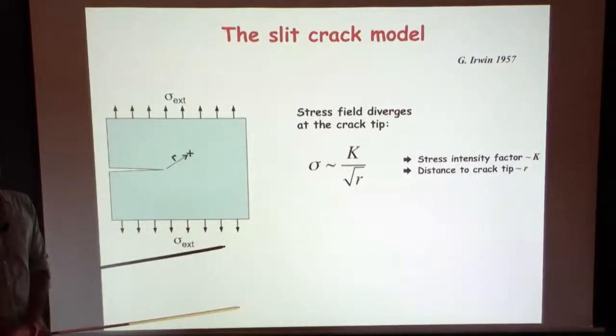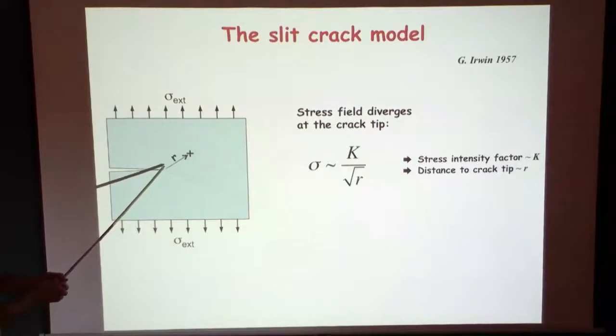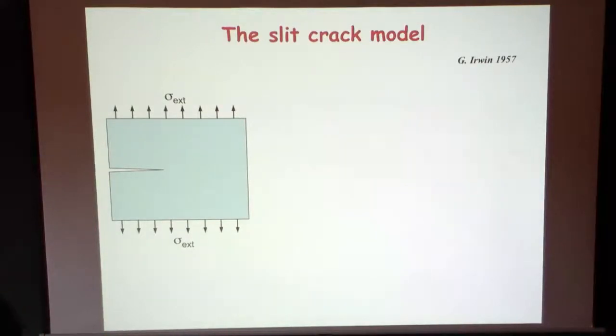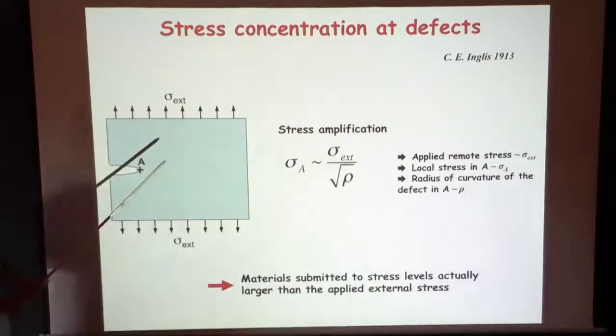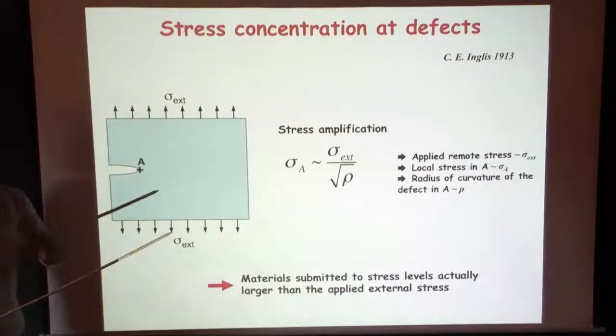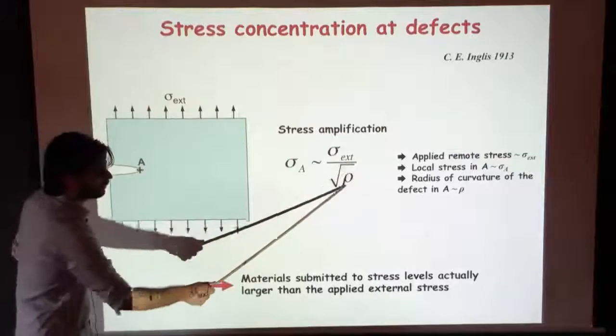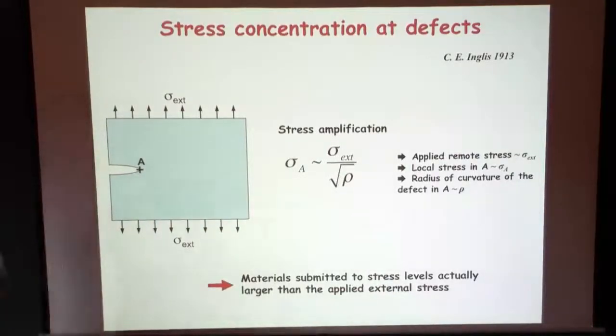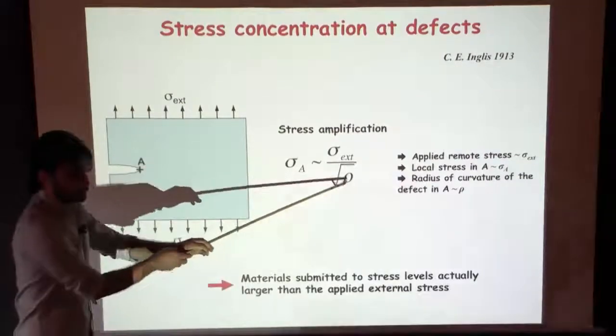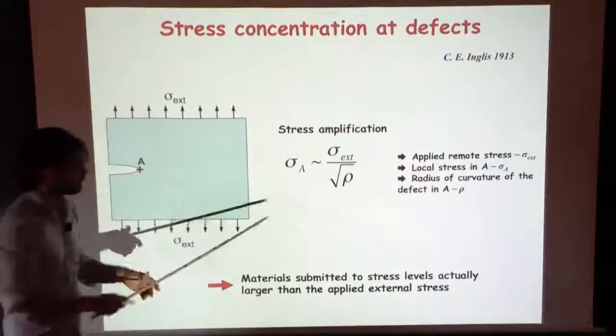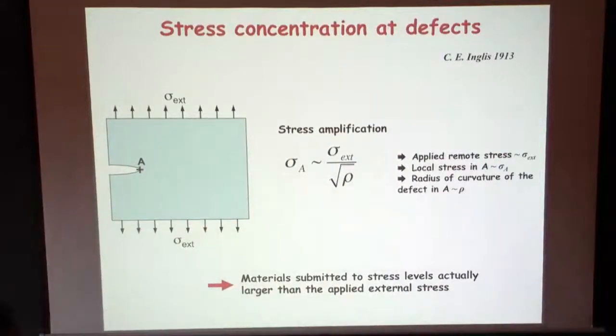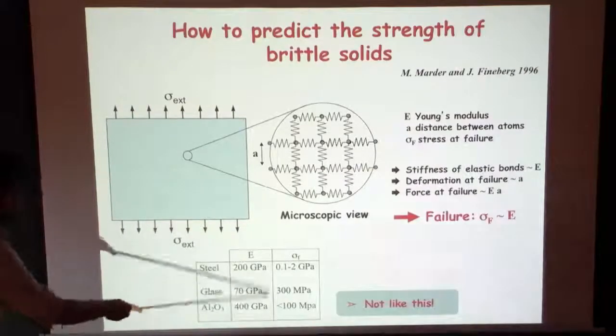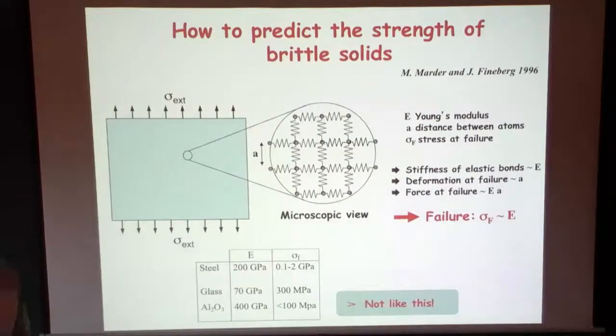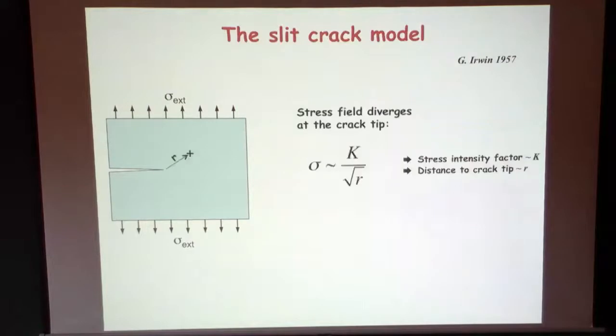So okay. What's the difference between this model and the previous model? The infinite is zero curvature. Oh, and that's finite curvature. Finite curvature, okay. Yeah, exactly. Rho is microscopic then here, right? Yeah, somehow this model is not completely irrelevant. In any physical problem you will have a length scale, at least the atomic scale, or you will see later, you will always have a regularization of this singularity through a material length scale. Not going to comment too much on that, but if you plug in a typical radius of curvature that you can measure on a crack, you can somehow rationalize a bit the two decades of difference you see between these quantities. But okay, let's move on.